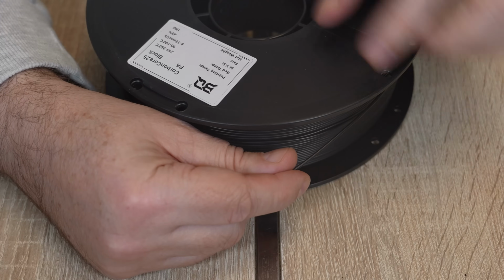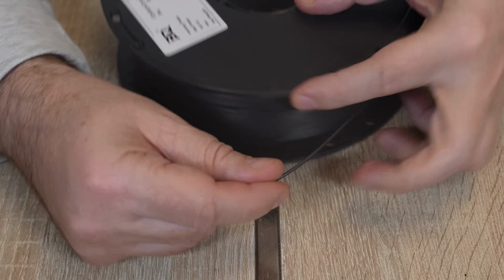And about the nylon, well, this is very special material. I can see a lot of possibilities in this material, but as I mentioned, it must be properly dried. But even in this, let's say, half wet state, it has quite good mechanical properties and layer adhesion. But first step should be done by the BIQU. First of all, dry the filament before the packaging, and after this maybe they should use some better packaging, maybe some alu foil or something like that.